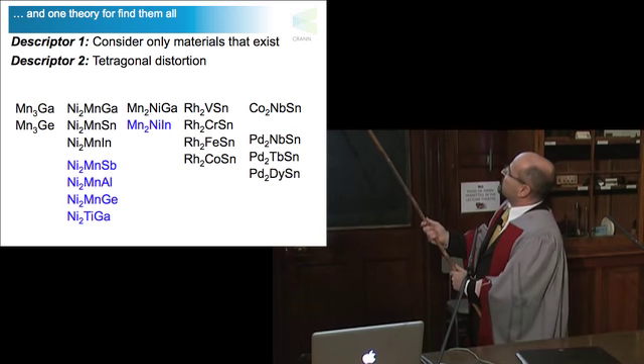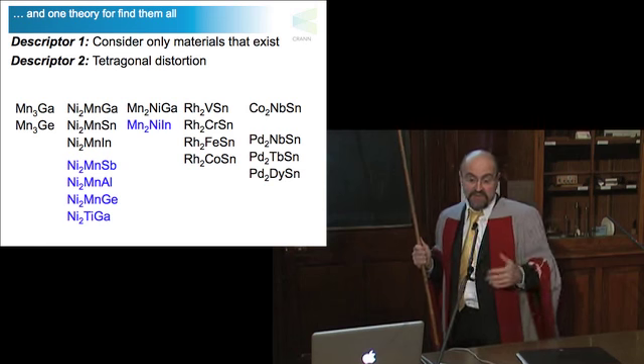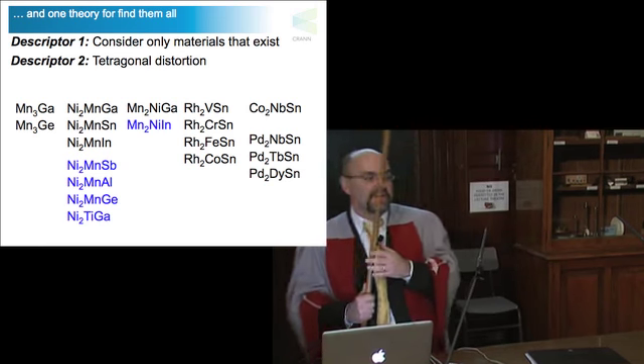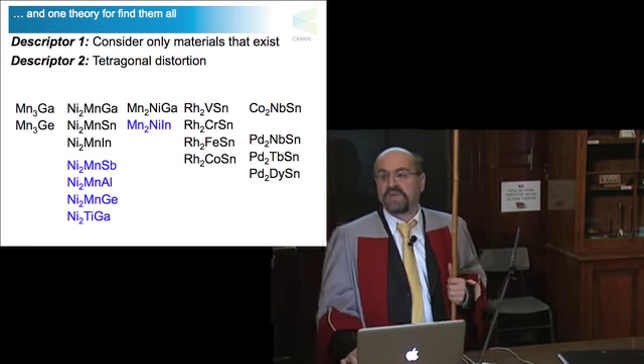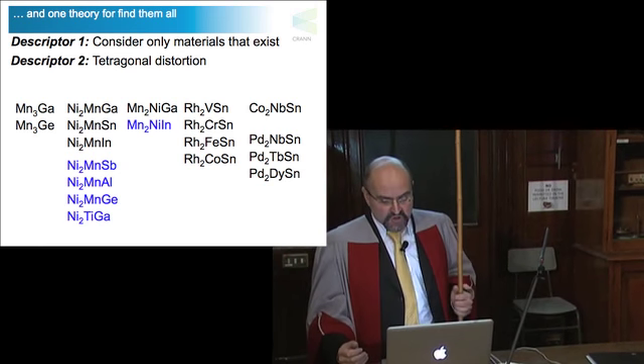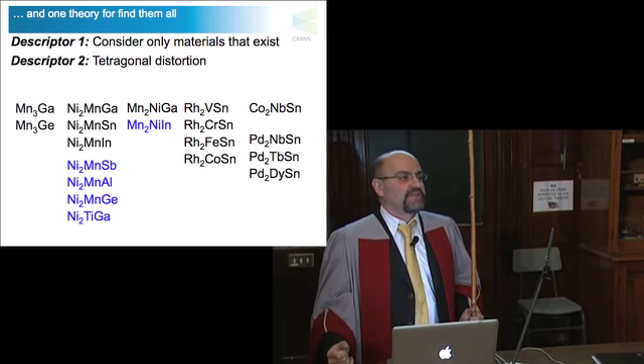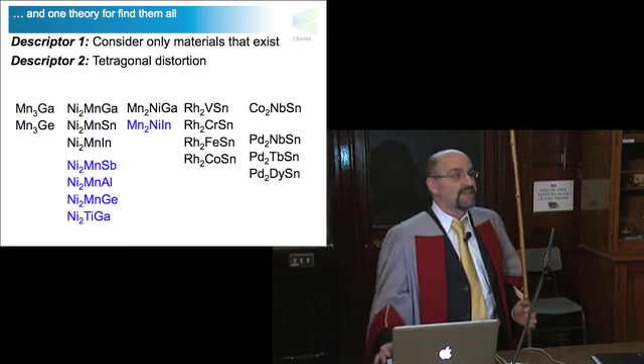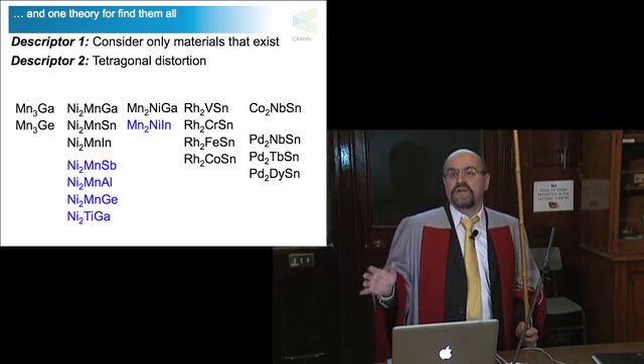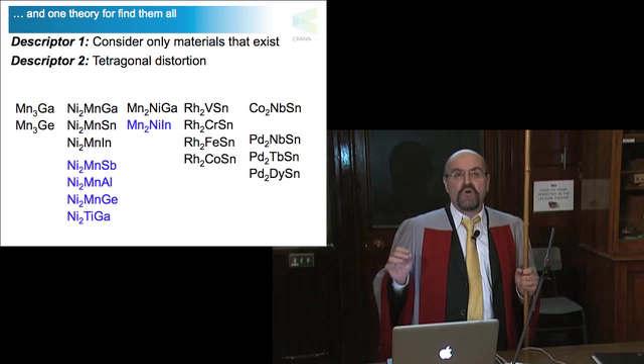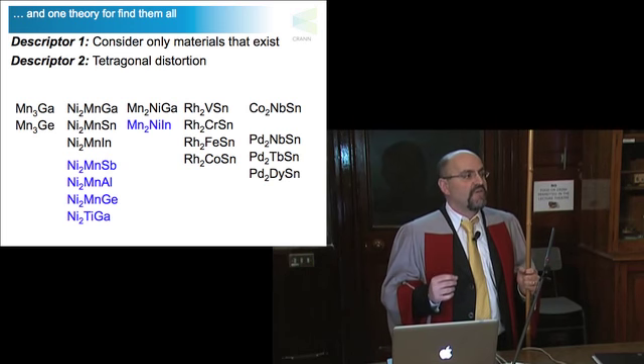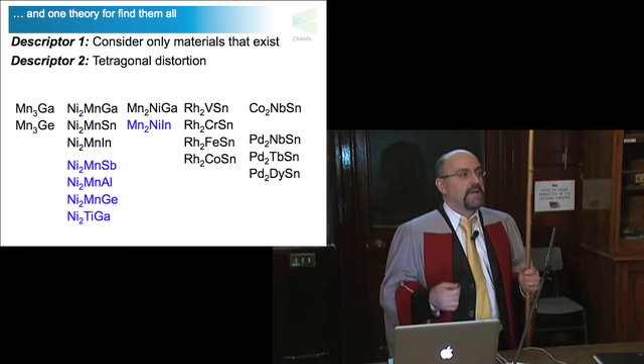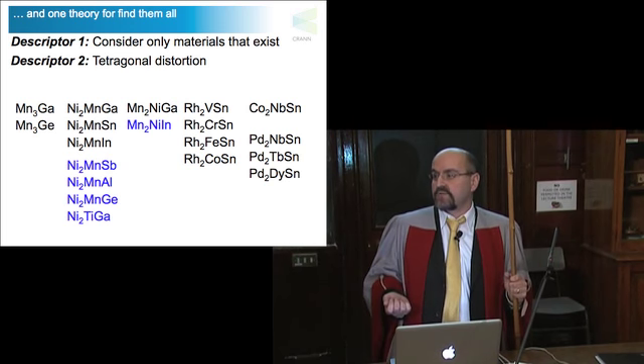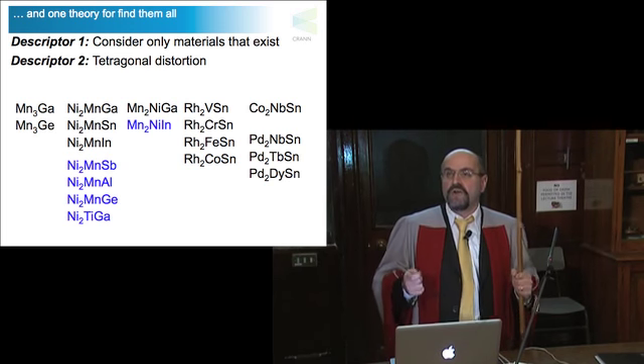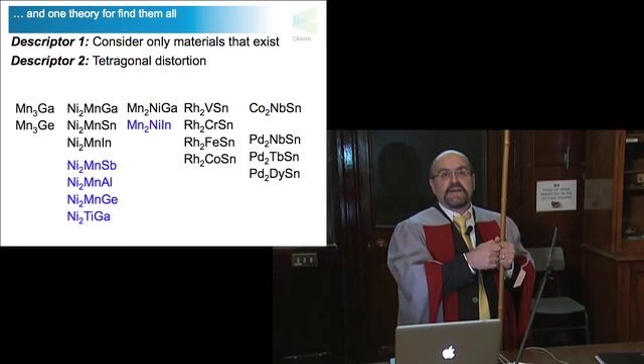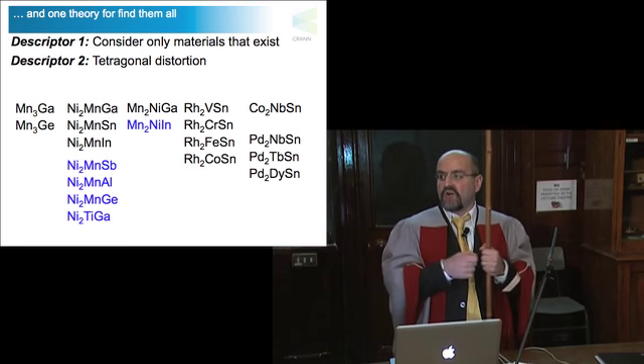Now, the ones listed are more than 13 because this blue one has never been made. It's just been calculated by others. So the black ones are the ones being made, and we found only 13. So the question is why this is the case. So we went back to the database. We looked for materials with this particular property of distortion. We found that in the hypothetical structures, many more of them can distort. And again, we tried to look at the electronic structures that they all share.